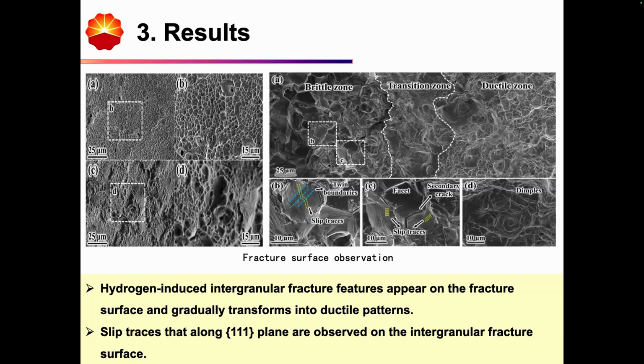For the in situ charged specimens, as the distance increases from the surface into the specimen, it gradually transforms from intergranular brittle fracture into a transition zone and then ductile fracture. If we enlarge the intergranular fracture surface, we can see facets, secondary cracks, and on the facets and intergranular fracture surface, slip traces along the 111 slip planes.